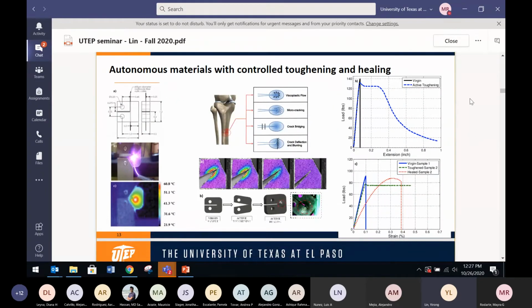This is something I find very interesting and feel very proud of. This is what I did when I first came to UTEP. What we are trying to do here is combine a shape memory polymer with a self-healing polymer as a biologically inspired material system. Here's how it works. To the left, as you see, there's a fiber optic running through the polymer, and this is a special polymer. It not only has a shape memory effect, but also a self-healing effect. Once a crack comes in, it's going to break that fiber optic, and then all the laser energy will be deposited at the crack tip. It's going to heat up the polymer. When the temperature increases, it's going to trigger the self-healing and the shape memory effect.